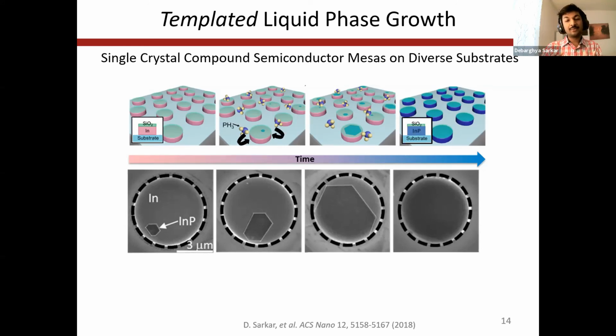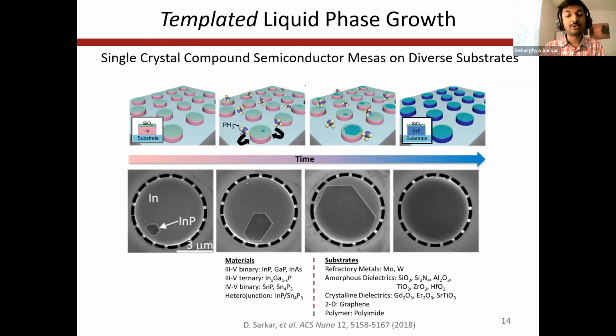Now, although I gave this example using indium phosphide as reference, it may be noted that it's not just indium phosphide that can be grown by this method. In fact, we have demonstrated a wide range of materials, such as indium arsenide, gallium phosphide, indium gallium phosphide, tin phosphide, and so on, and on a wide variety of substrates, including refractory metals, amorphous dielectrics like silicon oxide, silicon nitride, aluminum oxide, and so on, which are important materials for 3D integration, crystalline dielectrics, 2D materials like graphene, as well as flexible polymers like polyimide.